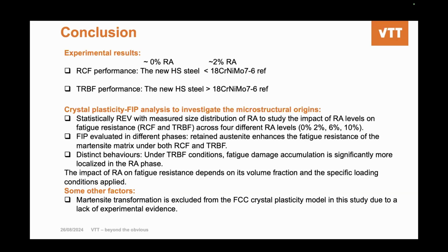So actually, the impact of retained austenite on fatigue resistance depends on its volume fraction and the specific loading conditions in general. And some other factor we haven't studied yet is the martensite transformation, because of lack of experimental evidence. We haven't done those studies at the beginning of this project, but it could be a project to explain those contradictory observations. And thank you for your attention.